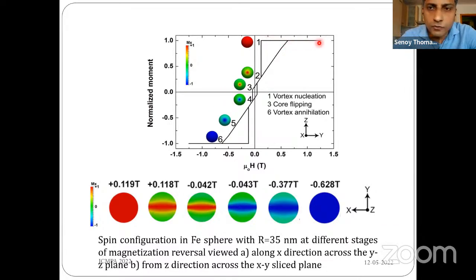So we also simulated the magnetization as a function of field curve for a single spherical particle. And what we found is that if you decrease the field from high positive values, then at an intermediate field you nucleate the 3D vortex with the core of the vortex pointing along the field direction. If you keep on decreasing the field, the size of the vortex core decreases. At one point, the vortex core magnetization flips, which results in a hysteresis in the MH curve. Finally, if you increase the field in the opposite direction, the size of the core increases, and finally at 0.6 it gets annihilated from the system, and we have a single domain system which is saturated in the opposite field direction.